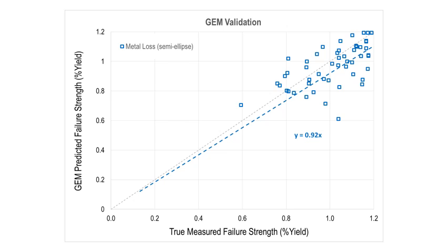The most refined model that I'm aware of for corrosion and metal loss is the PCORRC model that was put together by the TransCanada Research Group working with PRCI. And they managed to improve their algorithm to about 13% overly conservative, which is pretty good. Now, if you look at my accuracy with this semi-elliptical assumption, my accuracy I think is a little bit better than the PCORRC model currently is, but at this point I don't have particularly good precision.